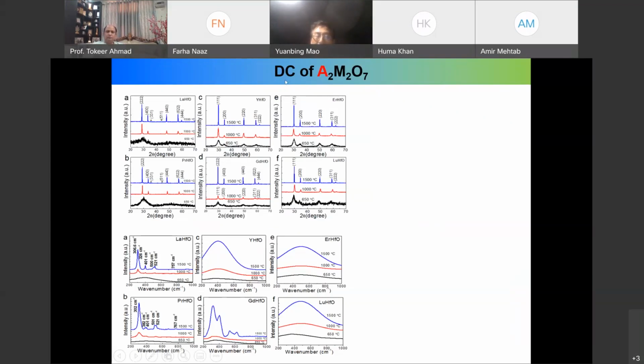So we use DC to represent the direct calcination. So you will see, for example, I'll pick this one, for this one, you will see for the lanthanum hafnate, right? By this direct calcination, the precipitate at 650 is amorphous, and only when the temperature reaches 1,000 or 1,500 degrees Celsius do we get crystalline samples, right? The other ones more or less have a similar trend. And then we also did the Raman spectrum, and you will see that if we look at the lanthanum hafnate again, at 650 this is more or less amorphous, and then after that we get this pyrochlore structure, right? Only at a high temperature can we get to that, right?